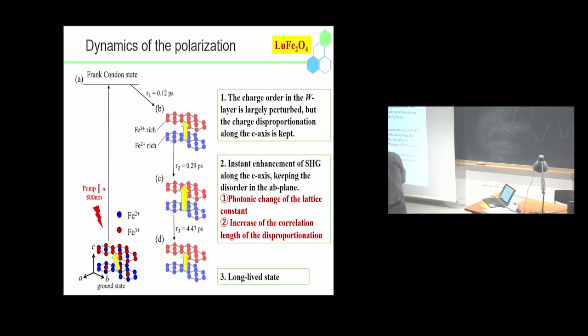Actually, according to the neutron diffraction measurements, the correlation length of the double layer along the C-axis is not so large, about 5 units or so. After the photo irradiation, if the correlation length increases, then the SHG along the C-axis can increase. At the present stage, we cannot conclude which is which. But I'm trying to measure the ultrafast femtosecond X-ray diffraction in these materials. And finally, we observe the long-lived state in which the in-plane order is disordered, but charge disproportionation is preserved. And this is the anisotropic dynamics of the lutetium Fe2O4.